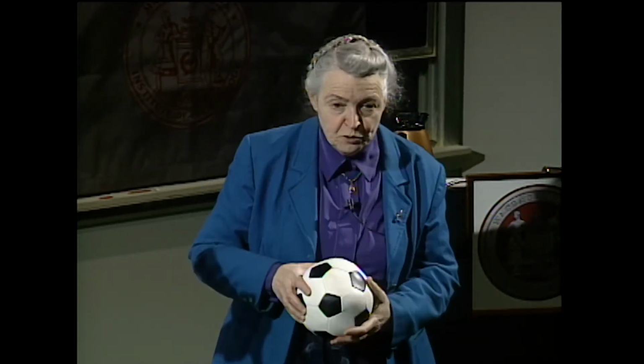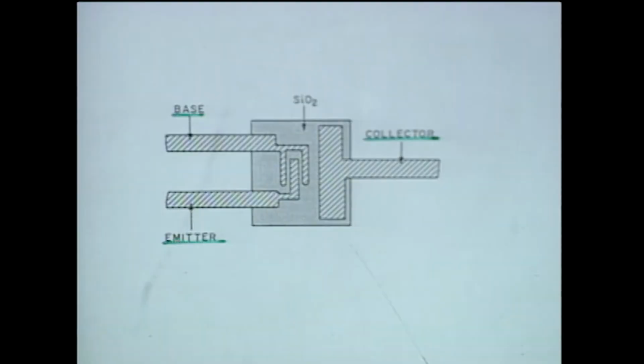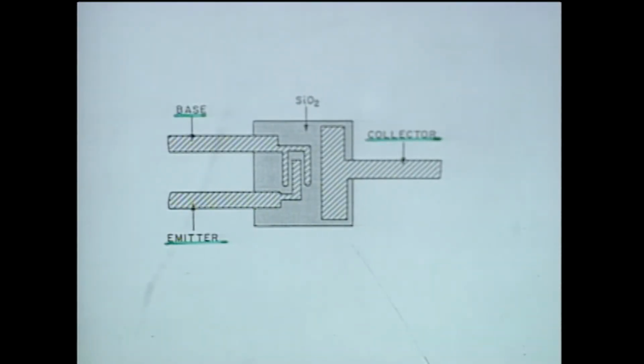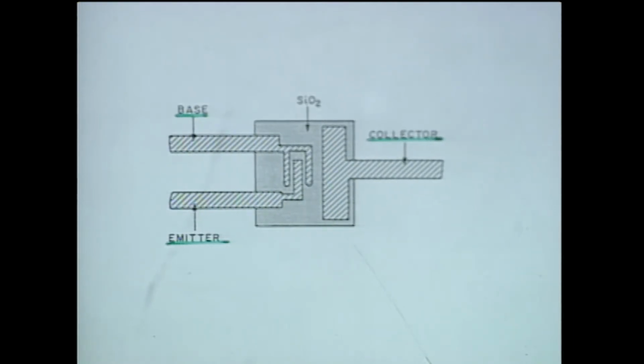Silicon dioxide doesn't have dangling bonds, so the buckyballs do not stick to the silicon dioxide. So if you have that transistor, for example, and you have a rain of buckyballs coming onto the surface, they'll stick only where the transistor place is, and where the silicon dioxide is, they won't stick at all. So like that, you can build up a surface. If you heat up the system, the silicon and the carbon from the buckyball will react and make silicon carbide, and you get a film. And the film is crystalline, as I'll show you in the next view graph.